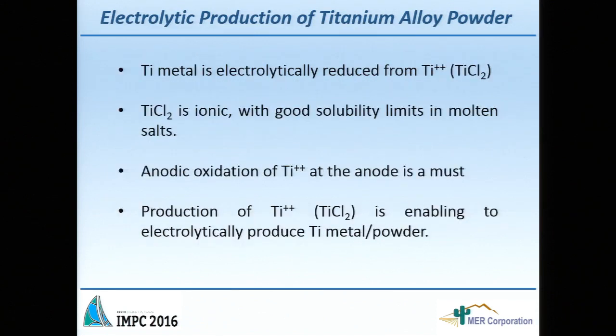what do we do? And really, what we need is one species of titanium in the electrolyte, and that's the TiCl2. TiCl2 is ionic and it has very good solubility, it can go up to 10 weight percent solubility in the electrolyte in molten salt. The other thing you have to have is that you have to prevent the oxidation on the anode side. So you have to use an anode at a potential that will not take Ti2+ to Ti3+ or Ti4+. And so the production of TiCl2 is really enabling to be able to produce titanium powder.